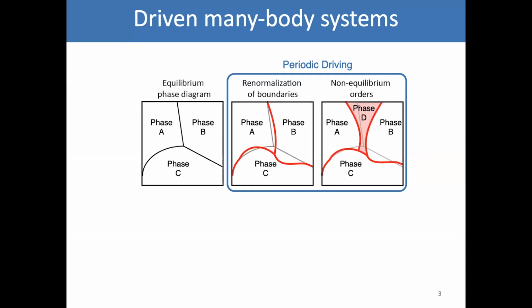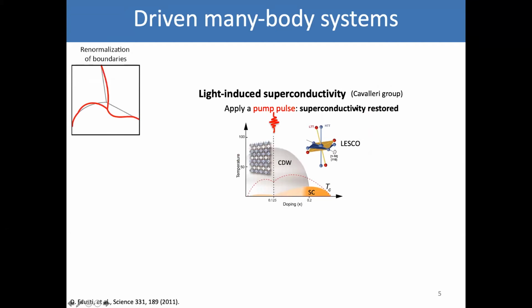So an example of phase boundary renormalization phenomenon is this light-induced superconductivity that was first discovered in the group of Andrea Cavalleri, also from Hamburg, where they look at this superconducting material LESCO, and they choose a particular doping and temperature where you don't expect to see superconductivity. So if you like, you are somewhere in this region of your phase diagram. I hope my cursor can be seen. Okay, great. It's good to know.